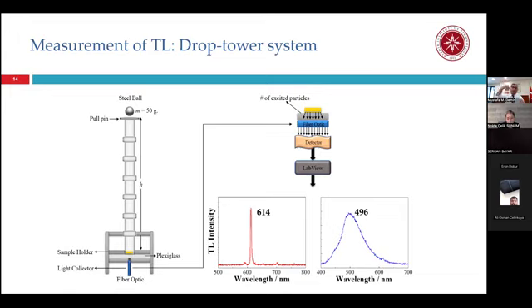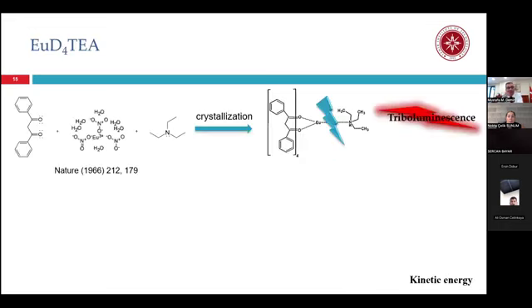So it undergoes a free fall. We know the potential energy turns into kinetic energy. So, free fall, basic physics. Then it hits the sample holder at the bottom, so we have a flash of light. Since this occurs in a dark box, it is possible to measure the spectrum via a fiber optic spectrophotometer. On the right-hand side, you see two representative triboluminescence spectra of red and blue emitting organometallic crystals.